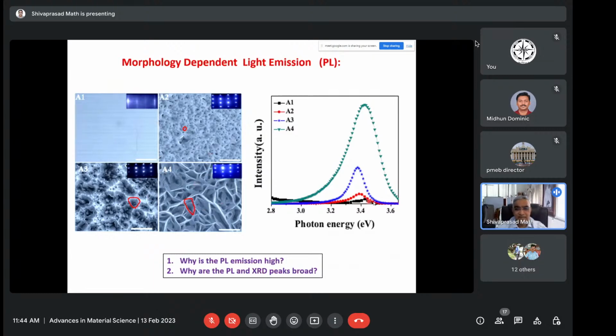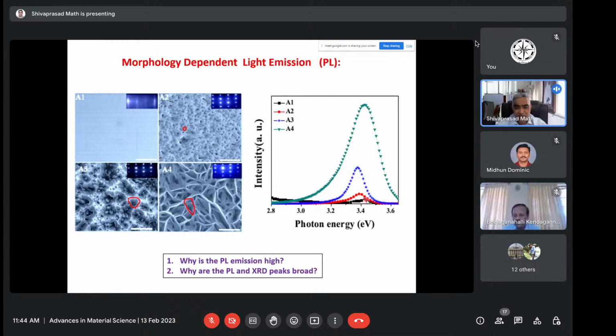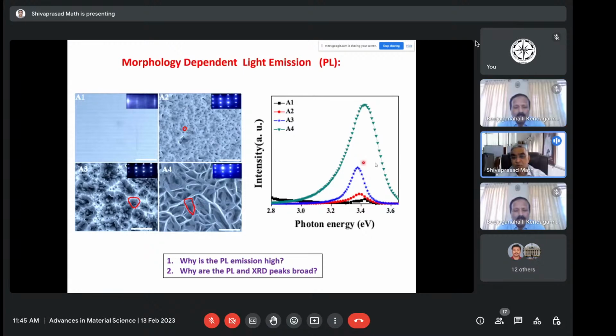Just to show you, the commercial material which is used for LEDs right now has a very small photoluminescence efficiency. But when I go on making it porous, you see here the efficiency increases. Very interestingly, this is nearly about 100 times larger efficiency in this material. Not only is there an enhancement in the peak height, but the width of the peak also increases. This is very surprising, because once the width of the peak increases, usually there is a fall in the intensity of the light from these materials.